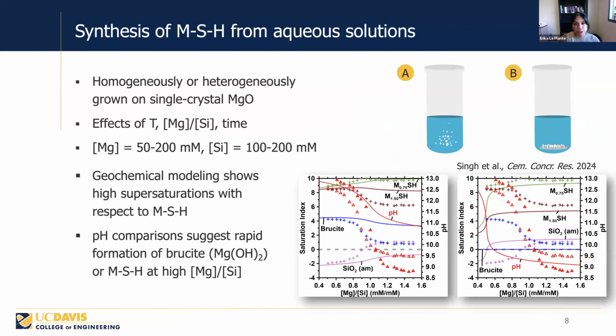So the first studies that we did is about the synthesis of MSH from aqueous solution. We take a solution containing dissolved magnesium and silicon, and then we grew this MSH homogeneously or heterogeneously on a single crystal magnesium oxide substrate. We looked at the effects of temperature, magnesium silicon ratio, and time for different magnesium and silicon concentrations in a solution. The first thing we ever do when we do a synthesis like this is to do geochemical modeling.